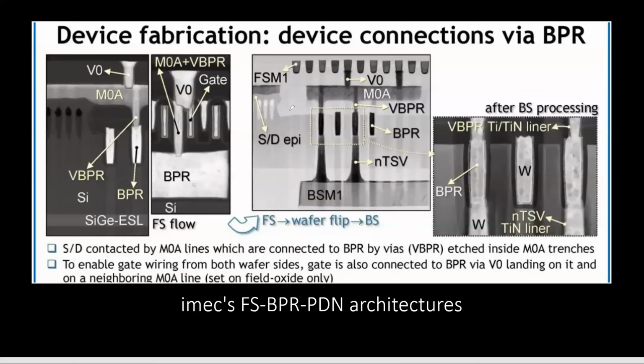And if you look at the IMEC, what they did, right? This is what they came out with in the talk. Okay, you could easily find it online. So pretty much this is all standard process. There are no surprises, except that for the power rail, they have to use tungsten. Right? You cannot use copper.